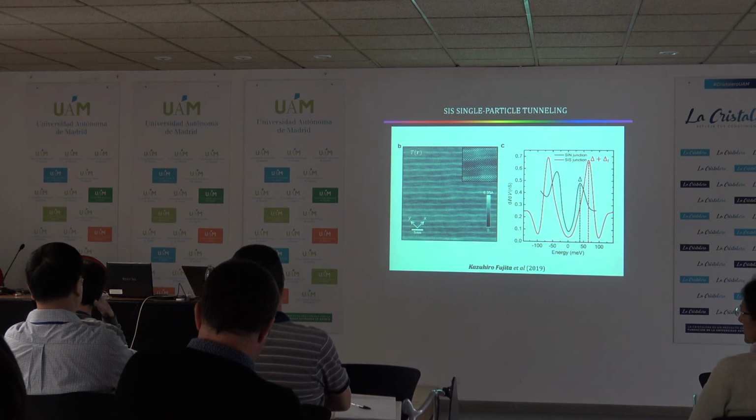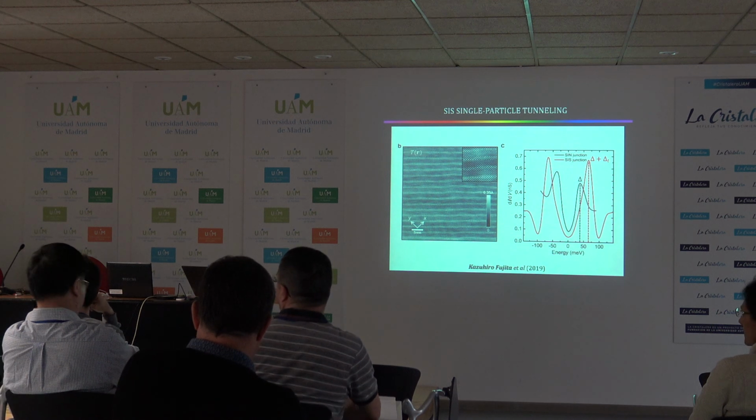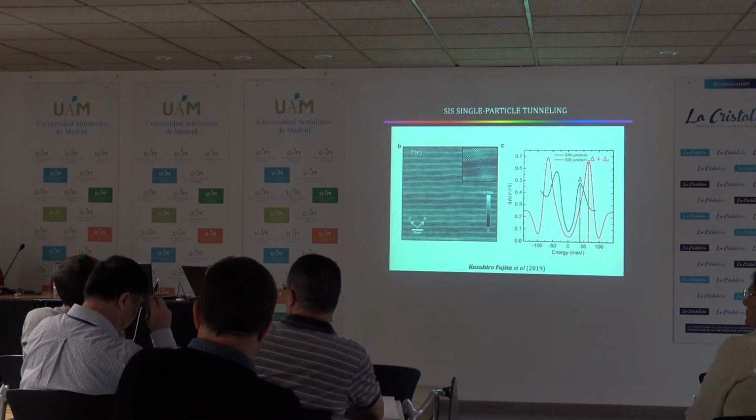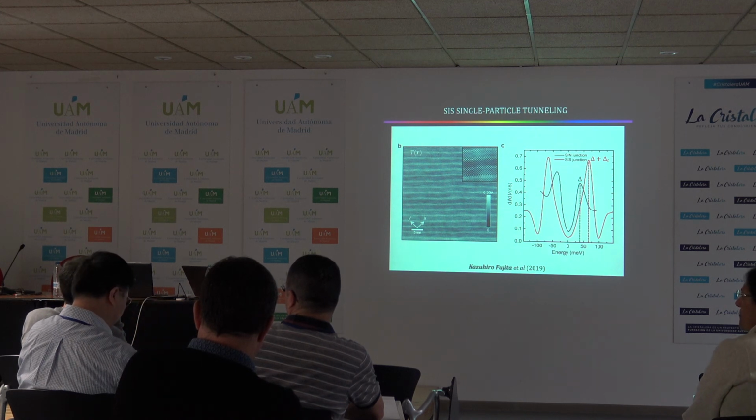So we can tell from repeating the topographs that the tip doesn't change when we scan. And we can tell from the moire pattern of the topograph that the crystals are aligned. The tip crystal is aligned to the bulk crystal. But the only experiments I show you here are the ones where that's true. There are many others where it's not true, and then those experiments don't work very well at all. You can do this, John. You could, but life is short.